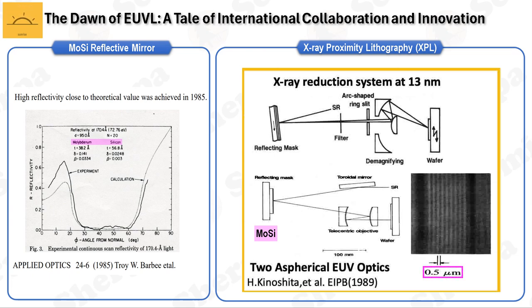By 1989, Kinoshita was ready to share their findings with the world. At the 33rd International EIPB Symposium in Monterey, California, he presented a 0.5 micron reduction pattern, suggesting the use of an exposure wavelength of 13.5 nanometers and incorporating two aspherical telecentric lenses into the design. His team from NTT took center stage with their paper, Soft X-ray Reduction Lithography. This was a testament to their hard work and innovation. They demonstrated the replication of a 0.5 micron pattern using the Schwarzschild imaging system and a reflective mask, achieving the ambitious resolution goals they had set.